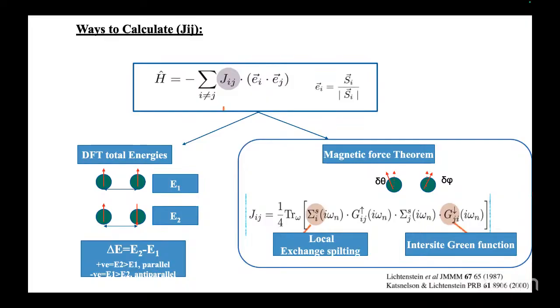Sorry, so these spins are iron spins, right? Yes. And I'm assuming that this effective ferromagnetic or antiferromagnetic interaction you get is because of the presence of the tin somehow, isn't it? Tin does not have that strong a magnetic moment. It's very small, around minus 0.11, so it doesn't contribute an effect. So in general, if I just have iron, then the interaction should be ferromagnetic, yes? We cannot say that, because the system can also have some kinds of frustration, as the geometry is, you can say, triangular.